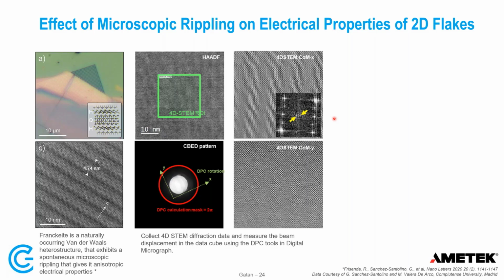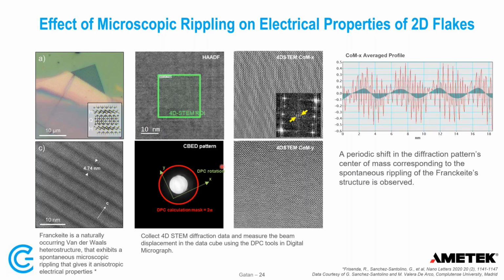They collected a 4D STEM data set. As I was explaining before, they looked at the shift in the center of mass, and then calculated the X and Y components. Looking at the profile of the ripples versus the beam shift, they found a nice correlation between the electric field and the ripples in their sample.